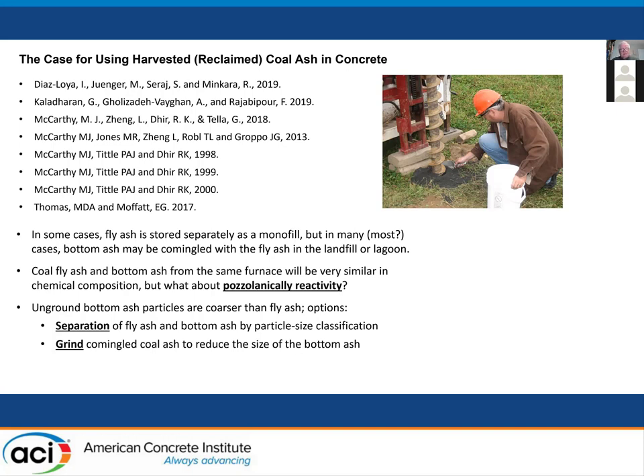Unground bottom ash particles are typically coarser, because they fall to the bottom of the furnace, as opposed to flying off in the gas stream. And so we've got two options here: either separating the fly ash and bottom ash by particle size, or grinding the co-mingled ash to bring it down to the fineness of fly ash.